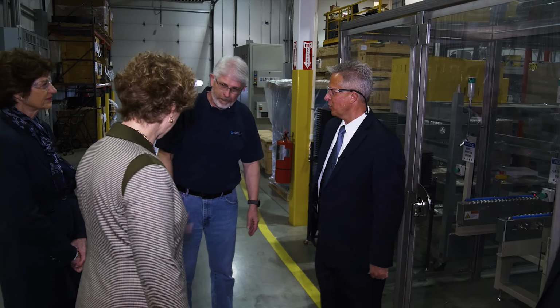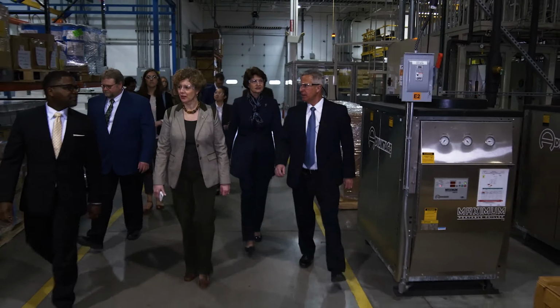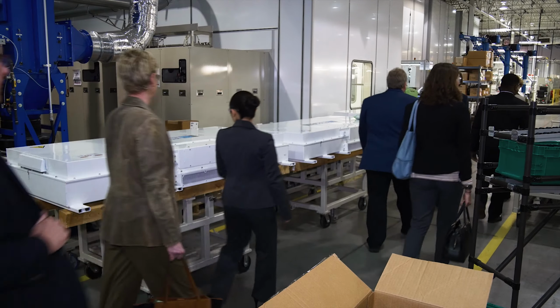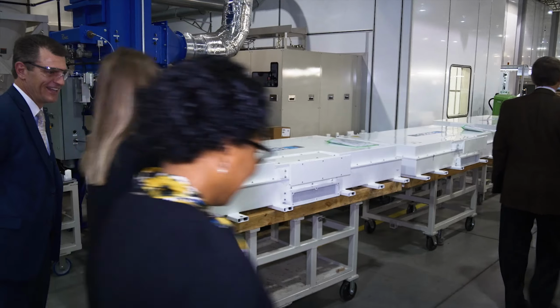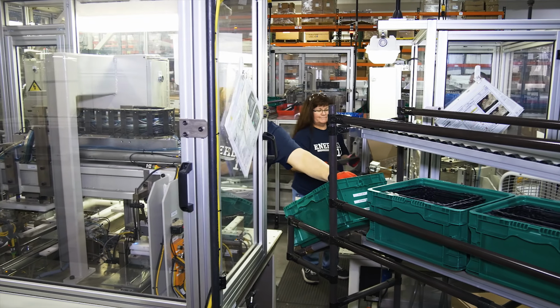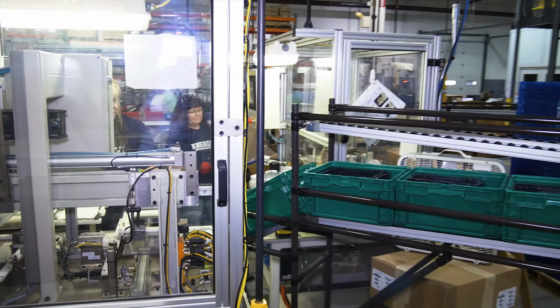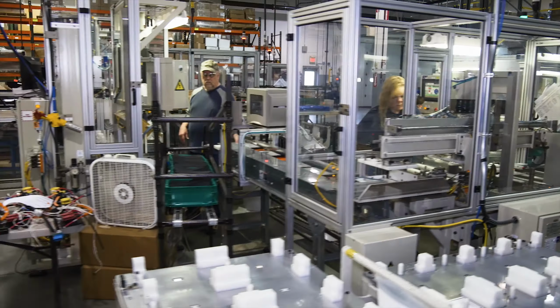Bruce, thank you very much. Appreciate it. We're going to take you into the dry room. It's approximately 15,000 square feet. It's actually a dry room and a clean room. We must keep water out of the cell. So these extraction ovens, their primary purpose was to extract any residual NMP and any residual water. So this is actually at a minus 80 dew point, or less than 1% relative humidity. So when we go in here, it's very, very dry. It's also a class 100,000 clean room. So it's very clean, it's very dry.